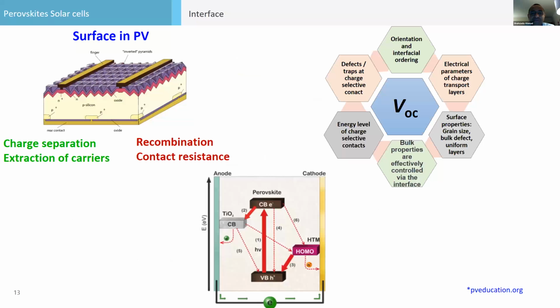So again, what is good for photovoltaic devices is very efficient charge separation, and the extraction of carriers should also be very efficient. What we don't want is recombination. We don't want electron and hole to recombine. It happens, we cannot remove it, but we want to slow it down. We want to change this, and the contact resistance at the interface. The contact resistance at the interface lowers the device efficiency. The recombination inside a device lowers the efficiency. But what we want is very efficient charge separation and extraction of carriers.